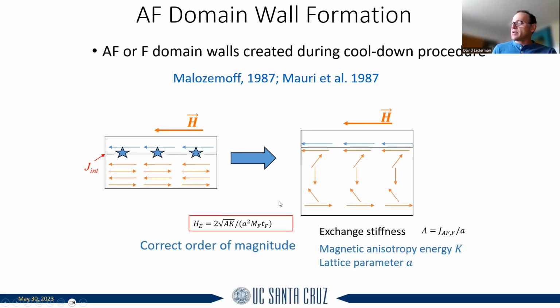And then another model has to do with what's called an exchange spring type of model, where when you reverse the ferromagnet and the antiferromagnet exchange at the surface is not satisfied, then what would happen is you would create some sort of domain wall. And there were different models. You could create a domain wall in the antiferromagnet, you could create a domain wall in the ferromagnet. And so in this case, it's kind of like a spring. It wants to go in one direction, and then as you go in the other direction, the spring kind of